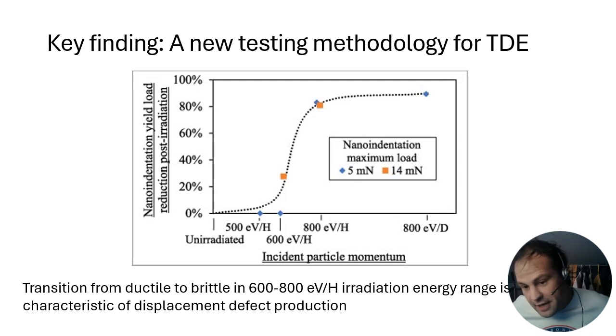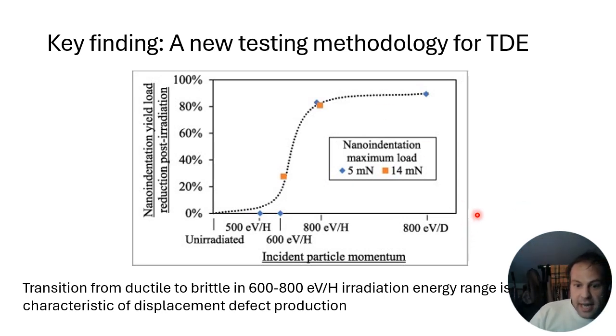Previous experimental validation of threshold displacement energy is not so high. That's been okay for fission purposes because using an average TDE of 40 electron volts, as is recommended by the ASTM standard, has worked out pretty well for reactor operations. But for designing next generation materials for new fission reactors, for fusion reactors, I think it's going to be important to get a better grip on TDE, in particular this crystallographic sensitivity to TDE. And this finding that nanoindentation is sensitive to effects in this very small kind of energy window really, to us, strongly suggests that nanoindentation could be a very useful, very high throughput means of assessing threshold displacement energy.